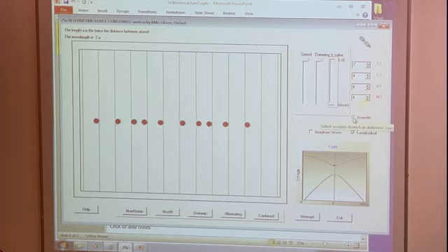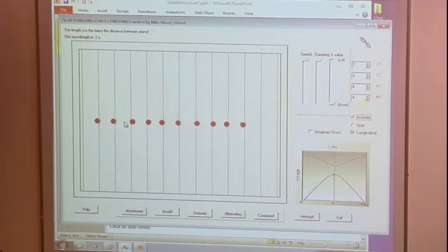Now, if you switch then from looking at the optical mode at the zone boundary to the acoustic mode at the zone boundary, it looks extremely similar, but it's lower frequency here. But you'll notice it's the other spring that's now getting compressed. You have one unit cell moving in one direction, another unit cell moving in the opposite direction, but now it's the other spring, the kappa 2 spring, which is being compressed rather than the kappa 1 spring.